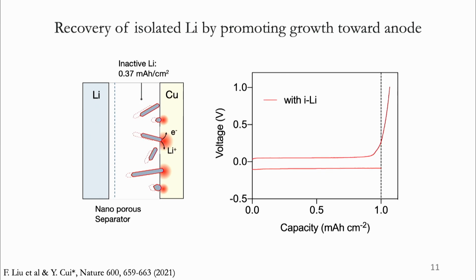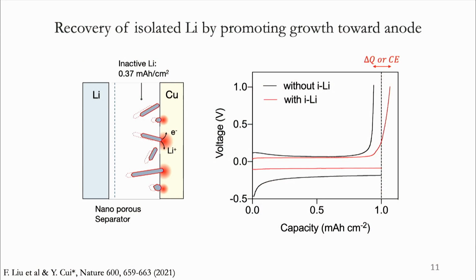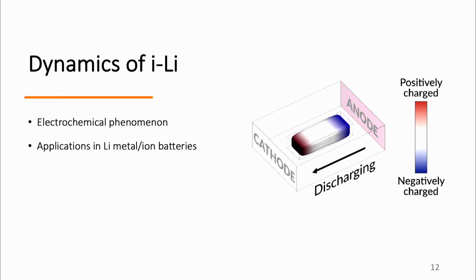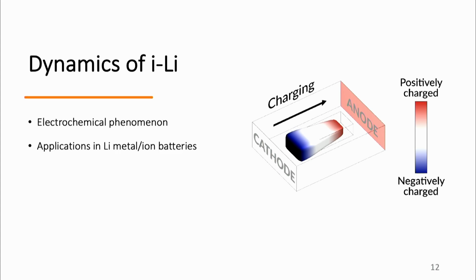Coulombic efficiency is the ratio between delivered capacity versus stored capacity. That means that the previous inactive capacity is actually being reactivated during the second cycle. Without isolated lithium present, the Coulombic efficiency of the batteries is usually about 92 to 93%. And the difference between those two cells is the capacity that we generated during this cycle. So this is a very, very newly discovered electrochemical phenomenon.